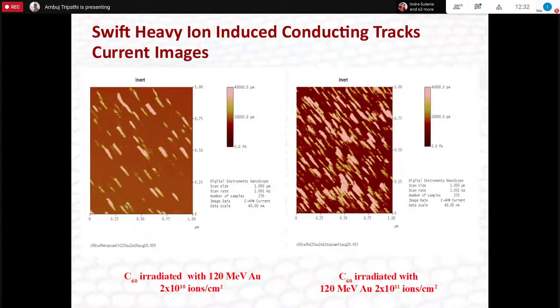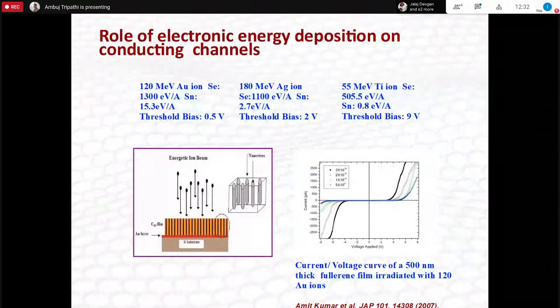So we looked into this, and we did IV on that. That was done by one of our brilliant PhD scholars, and it was part of the thesis of Dr. Amit Kumar, who did his PhD from here. He did this IV, VI measurement, I should say. In this measurement you apply voltage, you measure the current, and you see whether it is less insulating, so the conductivity should be more.